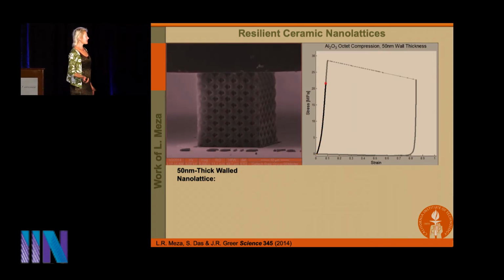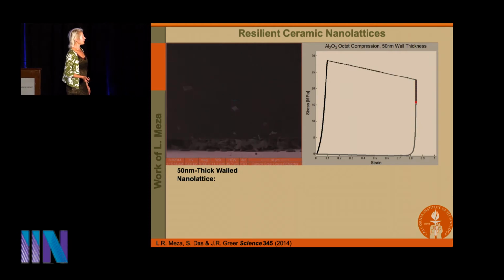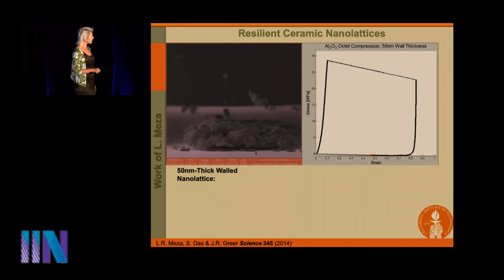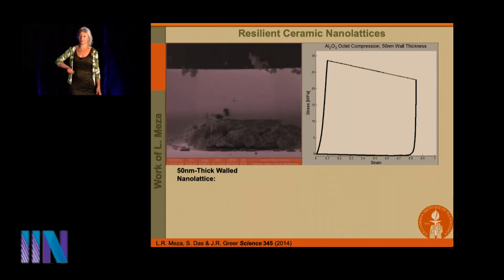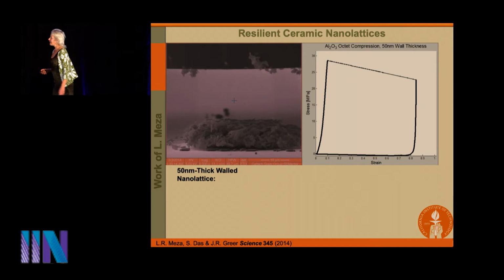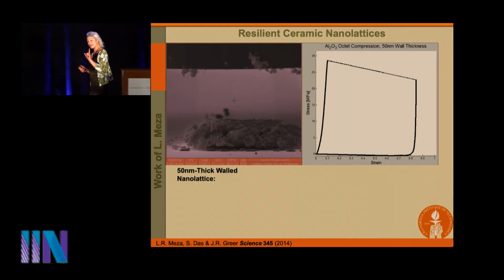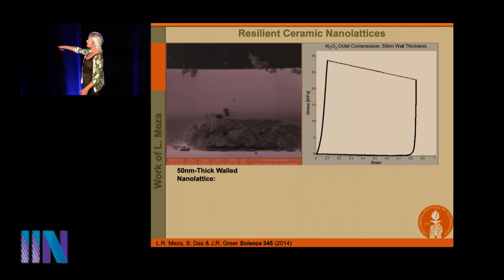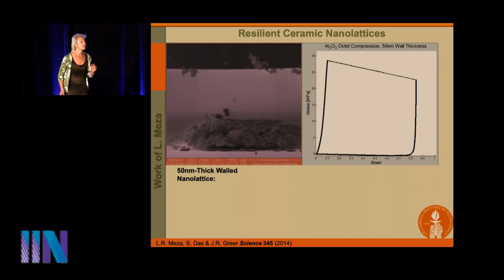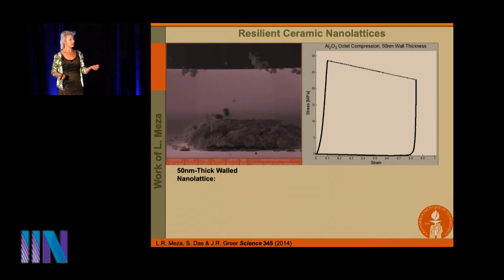So we're loading it elastically, just like we would expect, and then it crushes and dies, just like we expected. It's not even trying to recover. We have a little nanocemetery in our tool, and it's pretty much dead. There's only one good thing, and this is actually kind of important. If you look at the stress strain plot here, you can see that its strength exceeds 25 MPa. Something that's 99.9% air shouldn't have anything measured in mega units. Shouldn't be mega anything. You could be kilopascals or pascals, but this is 25 MPa, so it remains strong.